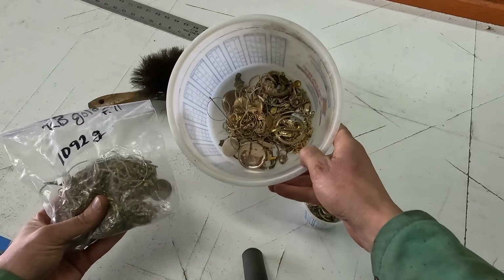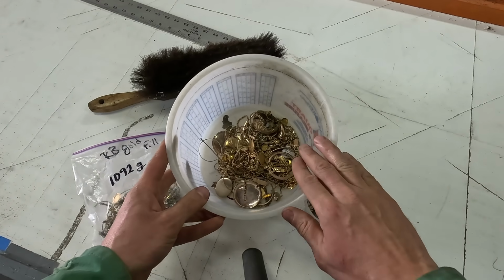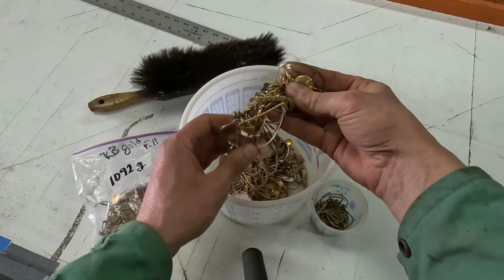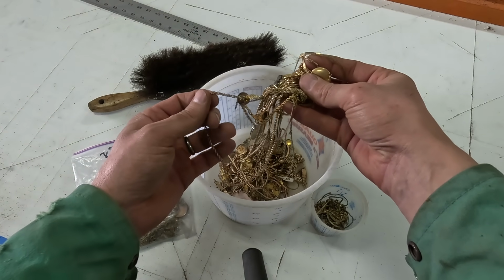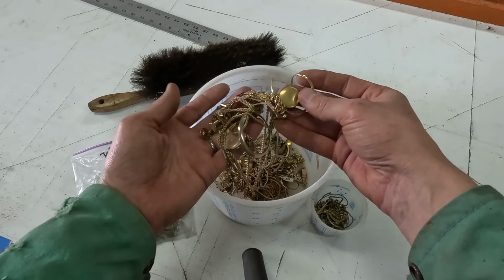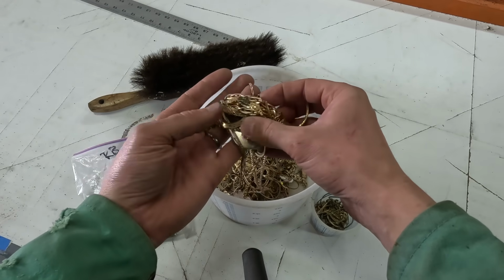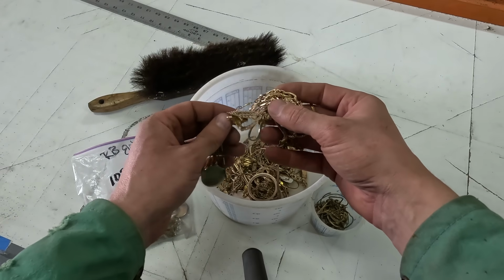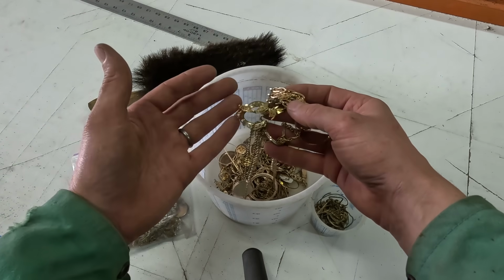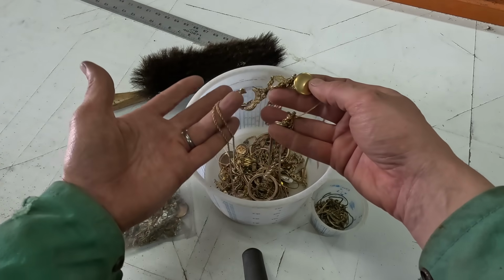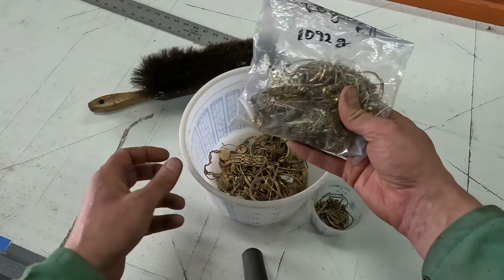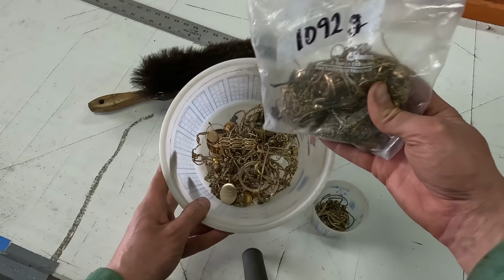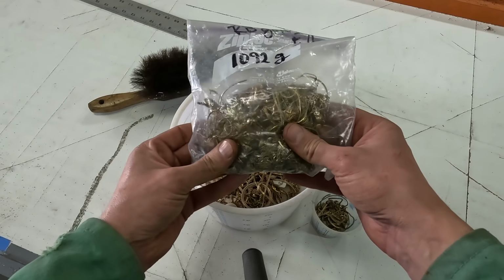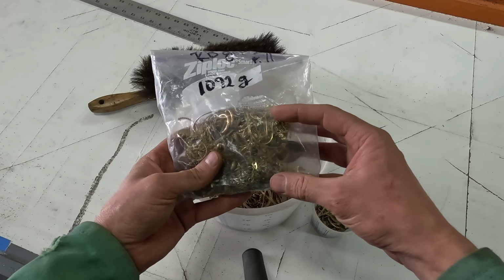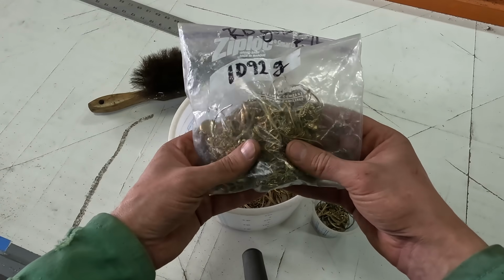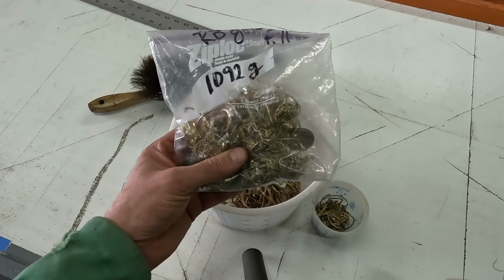So here is our gold-filled jewelry. Now this stuff is typically heavy gold plate over jeweler's brass, so mostly copper and a little bit of zinc. Traditionally what you do is you dissolve this in nitric acid. All the gold foil stays because the nitric doesn't dissolve the gold, and then you can refine out the silver and copper later. The problem is nitric acid is really expensive, and you would need gallons to do this kilogram of gold fill I have. So I'm going to try a new method. I'm going to weigh out 50 grams of this stuff to do a little test with it. Let's go over to the smelting lab and see if we can make this work.